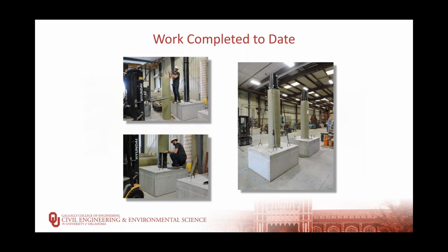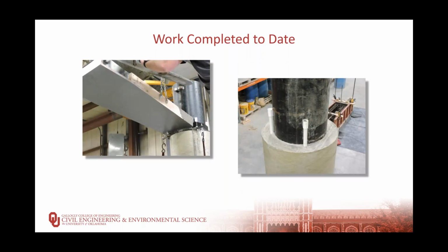We fabricated 2 specimens with high strength self-consolidating concrete. This SCC mix reached a 28-day strength of 10,000 PSI. It flowed very easily into the 8-foot tall column from the top. It required no external or internal vibration to fully fill the annular space between the steel tube and the FRP tube.